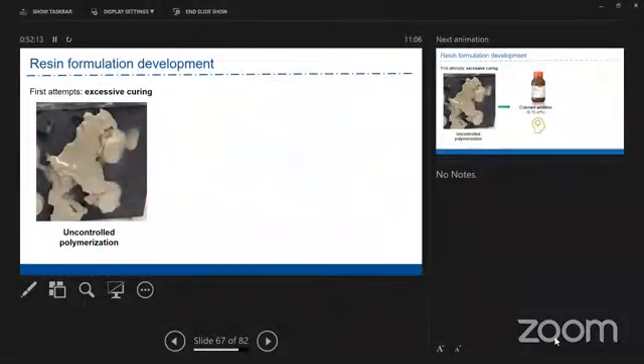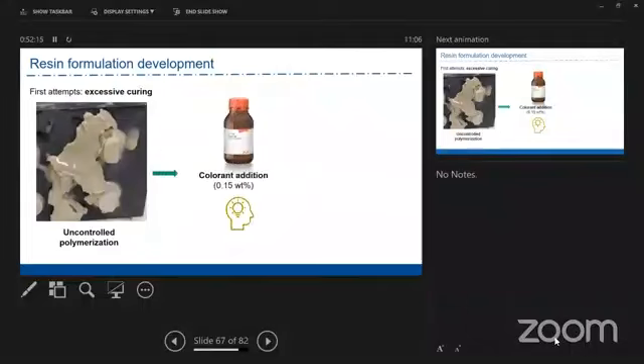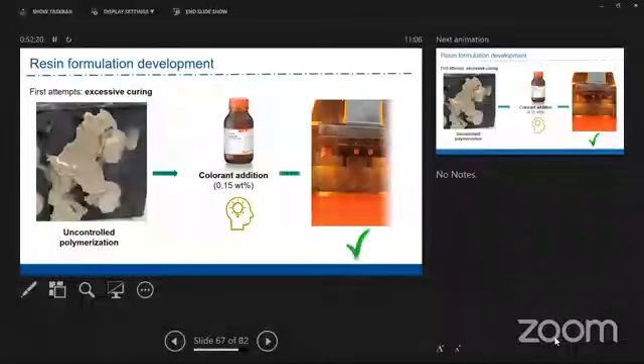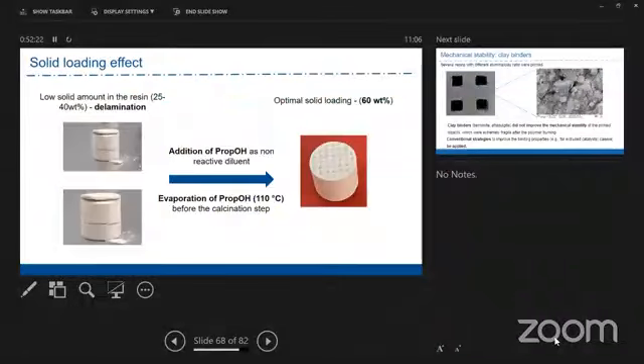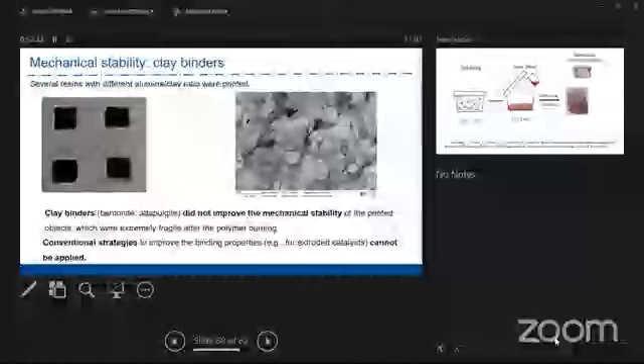Otherwise, if there is excessive curing, we might have some uncontrolled polymerization, and we added some colorants. Then the next idea was to add isopropanol as a non-reactive diluent, evaporate the propanol before the calcination step, and then we came to something reasonable with the optimal solid load of approximately 60%. So it's mechanically stable.